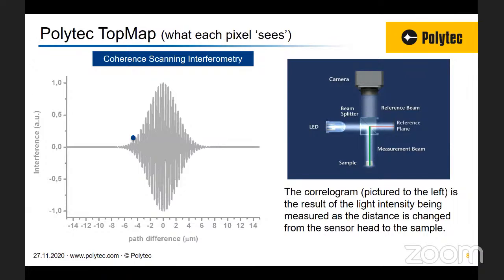We do this for each single pixel on the camera detector. By scanning through the surface, we capture the intensity signal coming back and collect that information. Then we look at the phase information contained within the coherent scanning, and we signal process this correlogram information. By doing so, we can go beyond the diffraction barrier of light and get sub-nanometer signal processing in Z. So effectively, we are identifying the best focus of a surface.